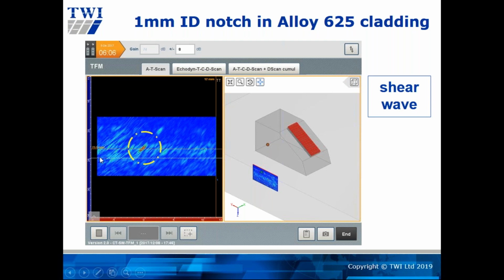I don't know if you can see my cursor, but this white line is pointing out the back wall, so the inside surface of the cladding. This tool is applied obviously from the outside surface of the pipe, and this cursor represents roughly the position of the flaw. The cladding itself was about 5 millimeters in thickness, so it goes from 25 here up to about 20 there. So that's the nature of the cladding, and what you see is the backscattered noise from the cladding. So that's the shear wave.